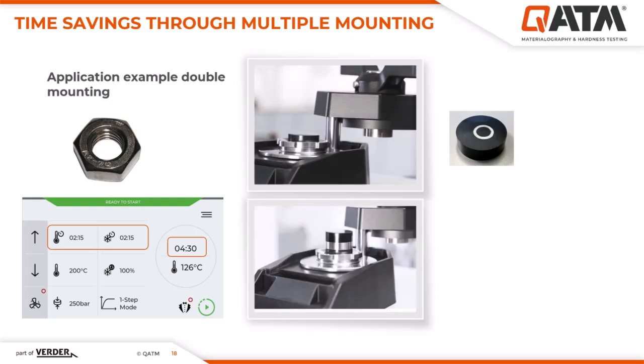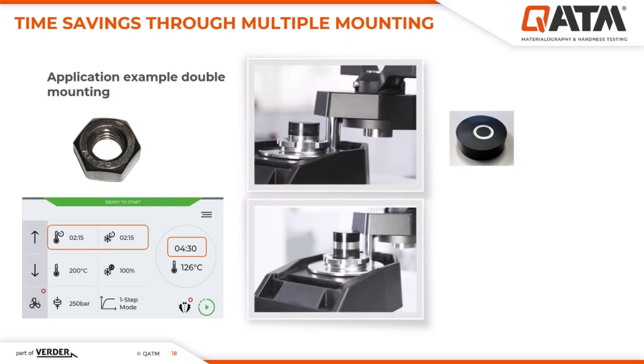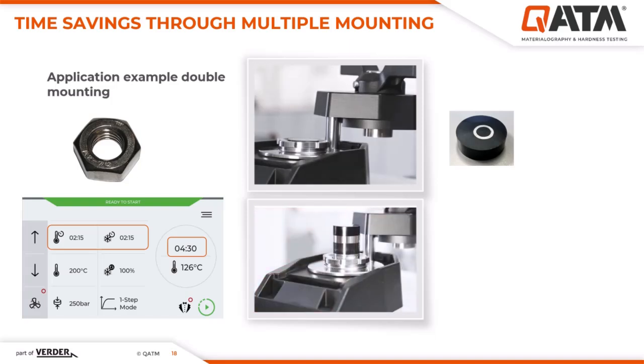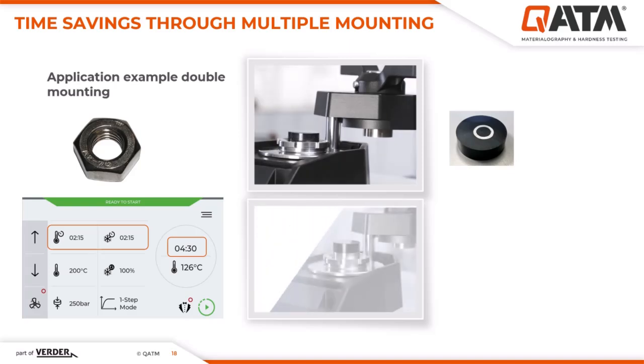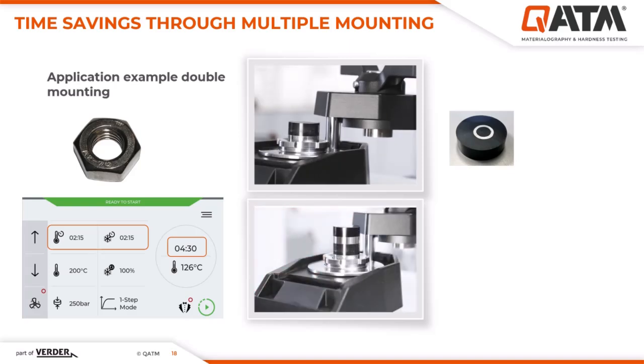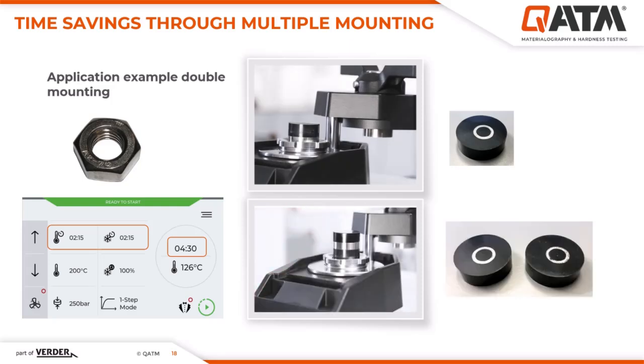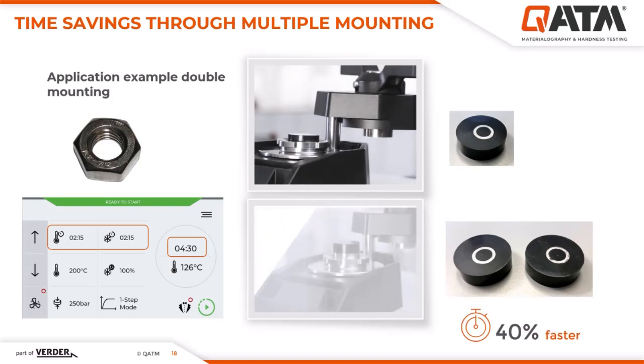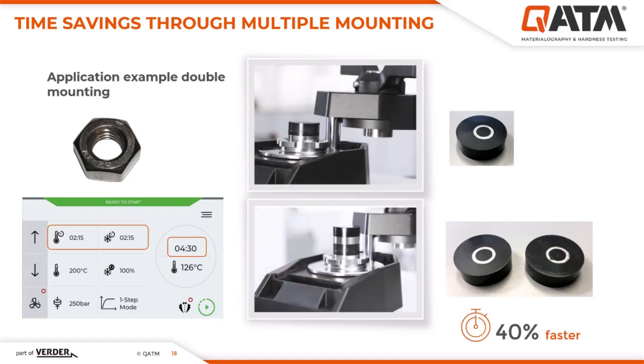In the example below, I did double mounting using the same parameters, but in the same time I mounted two samples. The insertion of the spacer pistons must of course be taken into account in the time comparison. That is placing the piston, inserting the second sample, and adding the mounting material for the second sample. But overall, however, the total time with double mounting was reduced by 40%.